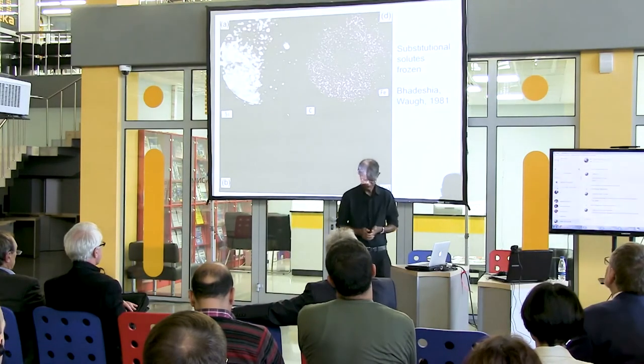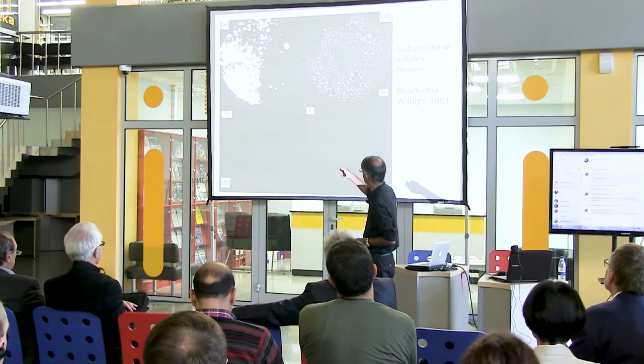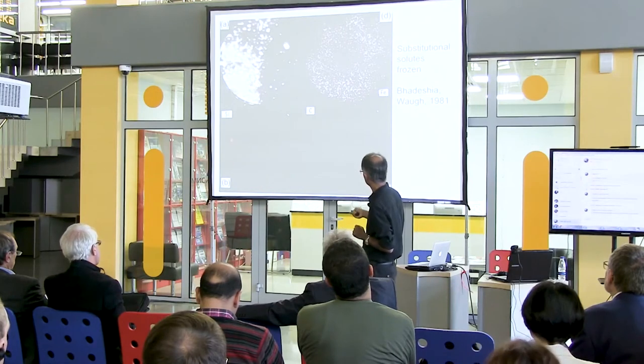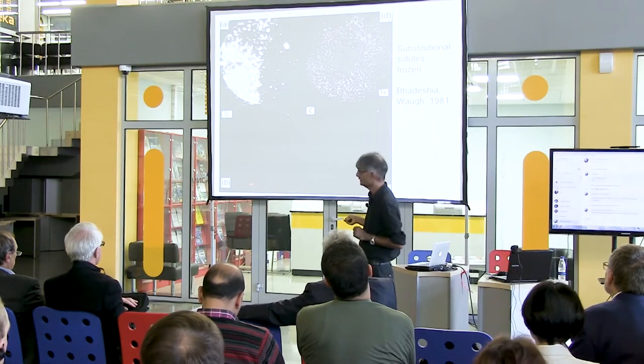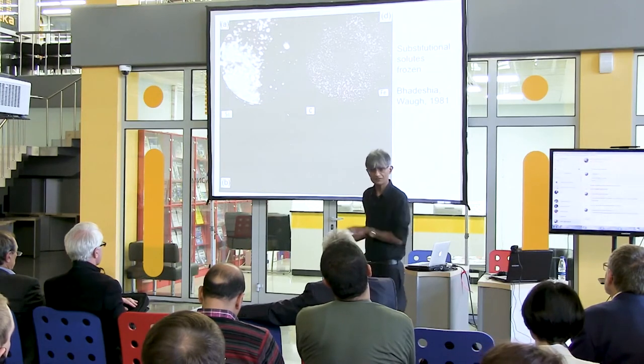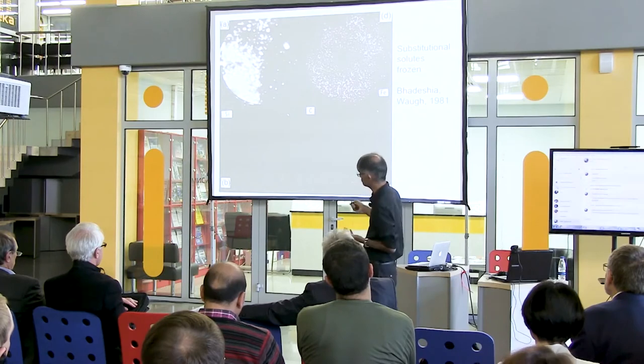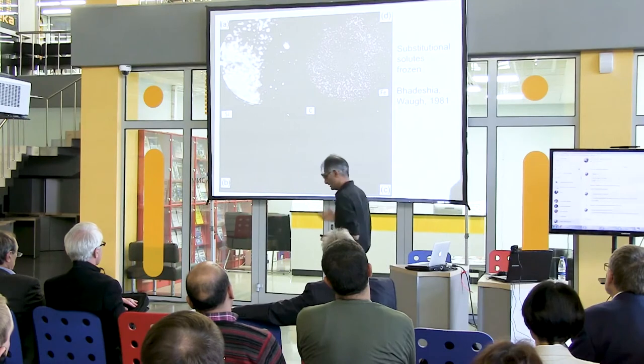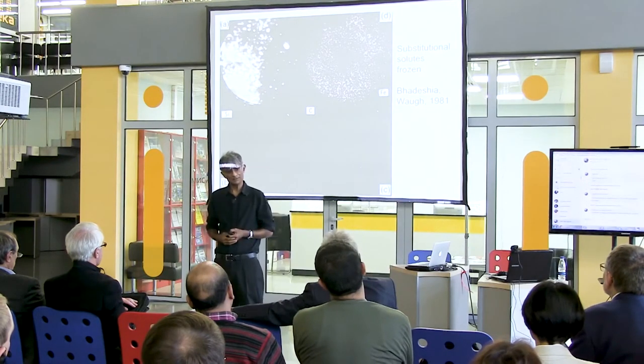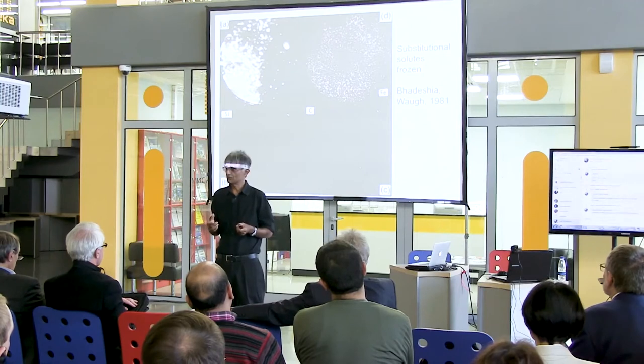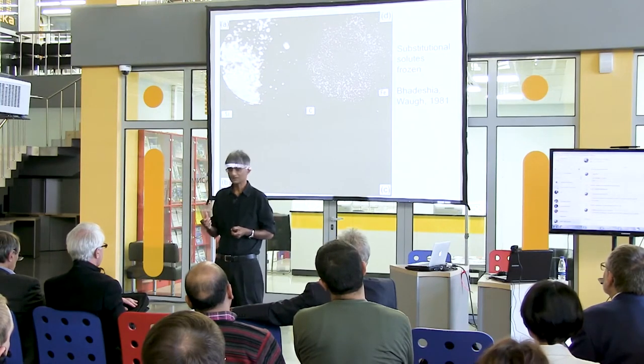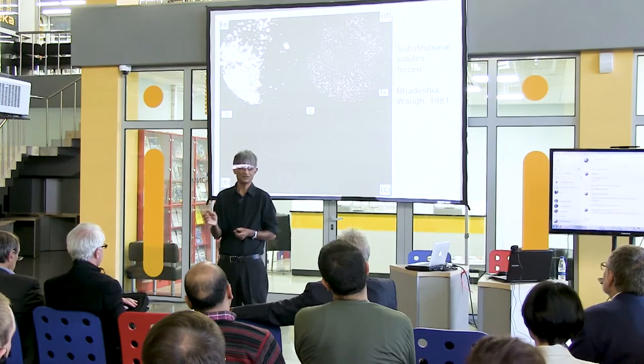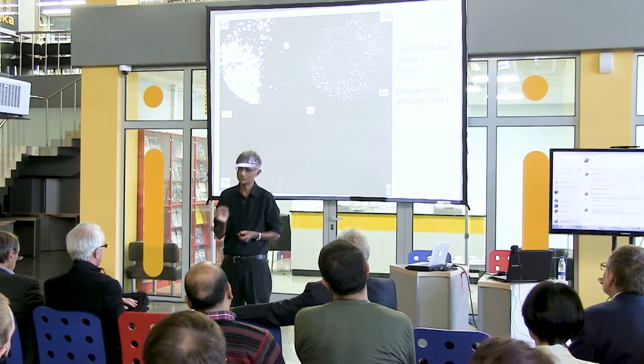This is a mixture of austenite on this side and bainitic ferrite on this side. Here we are forming an image with just the iron atoms, and here with just the silicon atoms and carbon. You can see that the carbon is on the austenite side of this image — each dot is a single atom. So you can analyze atom by atom. When I did this experiment, we collected 2 million atoms. That sounds like a lot, but in 50 grams of iron there are 10 to the power of 23 atoms. So it is negligible — less than a piece of dust, the amount of material we are looking at.